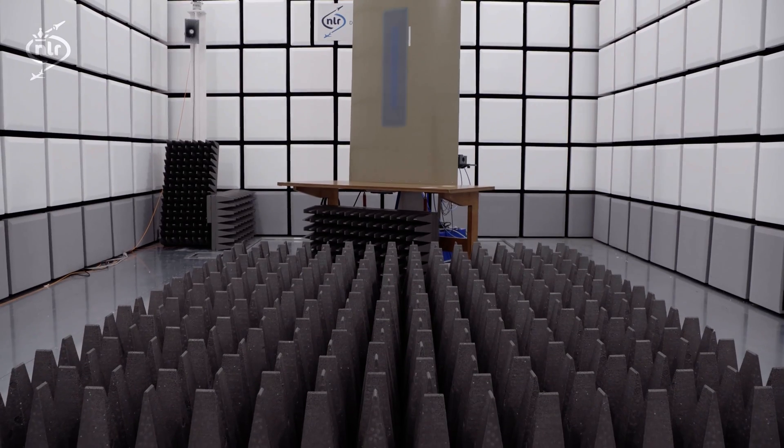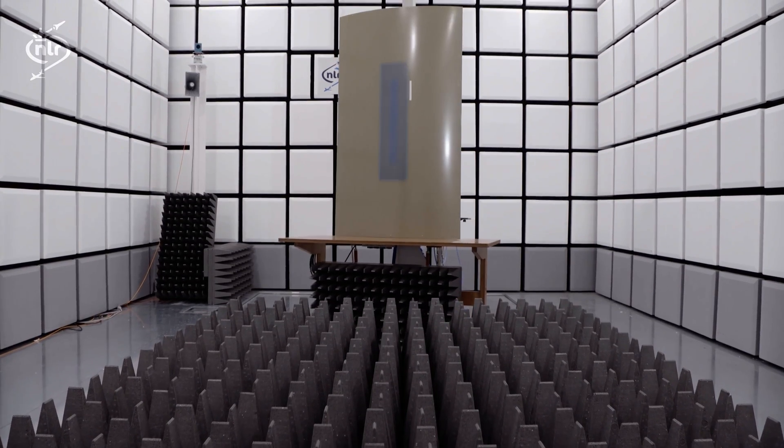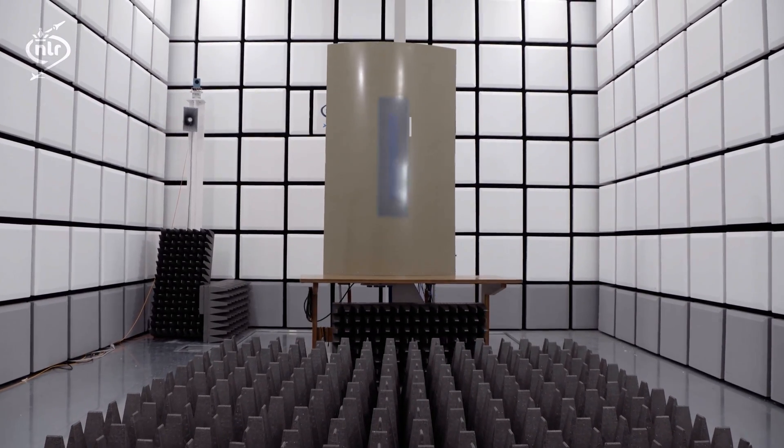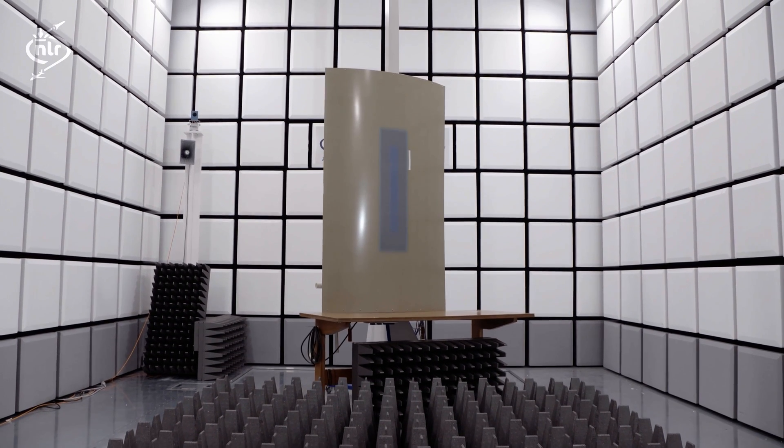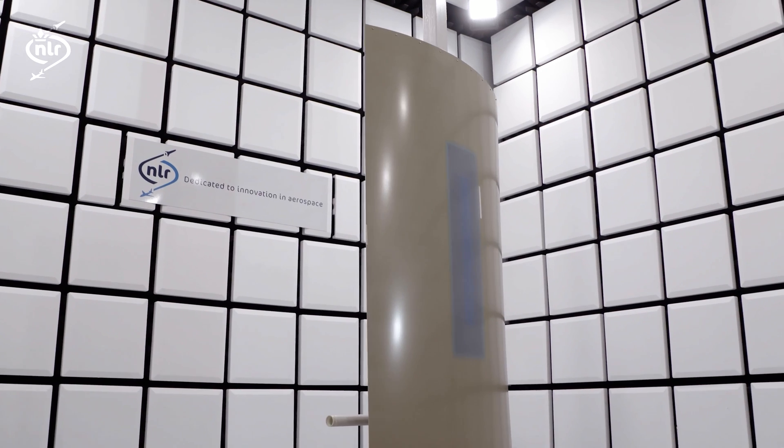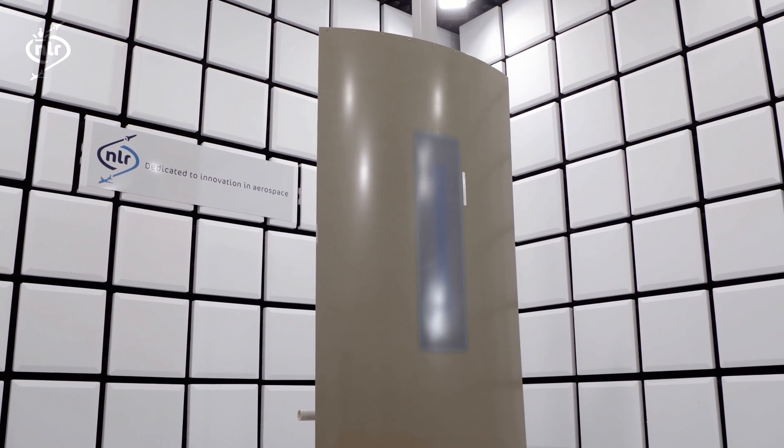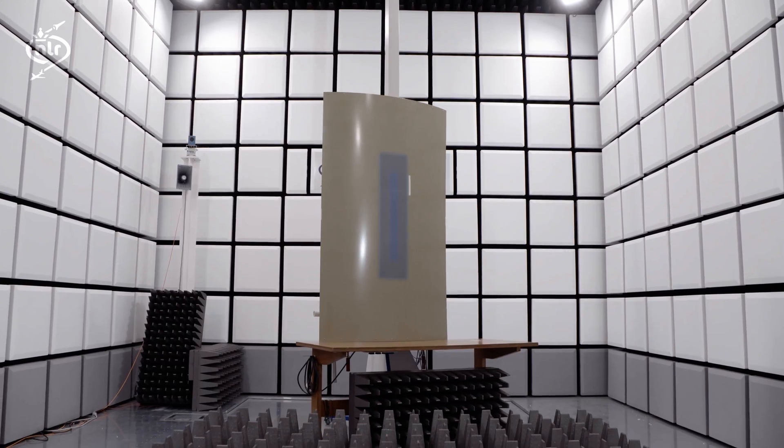The second innovative structure is a fiber metal laminate fuselage panel with a conformal and integrated VHF antenna. This antenna is obtained by a slot in the fuselage skin and by adding a so-called parallel plate resonator box. The slot is covered by extra glass material and moreover reinforced by extra glass layers. This is to avoid high deformation and stresses that can occur due to the pressurized fuselage loads.